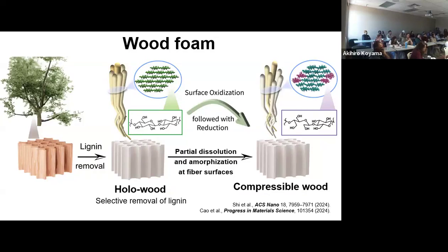Okay, maybe one more example of things that we can do with wood, just working at the interface, adding water and removing water. The last example: this morning I was discussing a lot of foams. There is a foam here that is very simple to make, and it's an interesting one that I propose to you. Same concept. We started with wood. We remove lignin, and the lignin can go to somebody else to work with. And then that piece of wood we can call holo-wood. In this particular case, we make sure that we preserve all the cellulose and the hemicelluloses. So this is a high-yield material. We lose 30% of the material by way of the lignin that is removed, but the remaining is structurally the same components, and they preserve the structure.